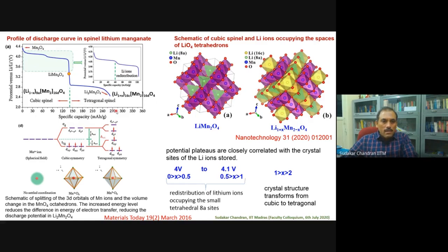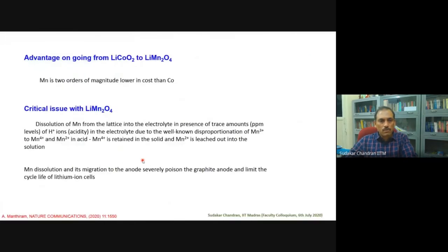This second lithium insertion could not be utilized for practical applications for the reason that it undergoes a tetragonal spinel structure, which has a huge structural distortion, and therefore the material pulverizes. So you cannot practically utilize the extra specific capacity you can store. So that still remains a challenge till today.